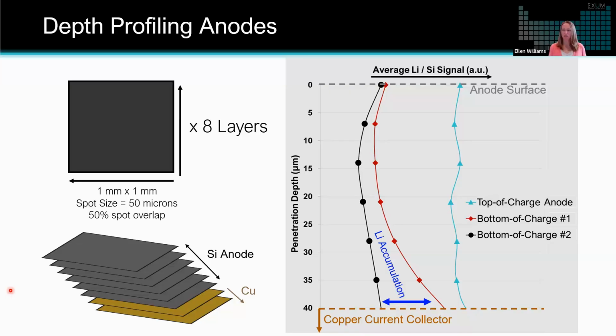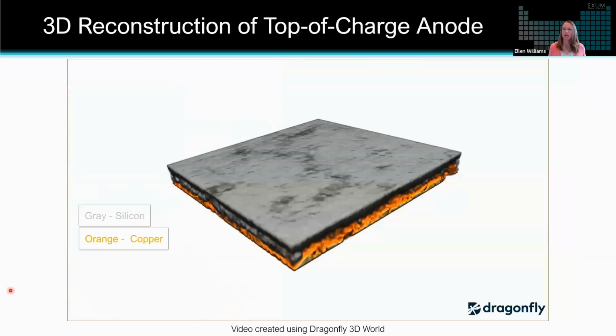So is this lithium accumulation potentially detrimental? Could this potentially turn into some lithium plating? All of this is very helpful to understand as you are developing an appropriate cell geometry and formation cycling process. Now, the final piece of the study that I want to show is what this actually looks like in 3 dimensions. So rather than just averaging and integrating across these different layers, let's take a look at each one of these voxels in 3 dimensions and see those different elements that were identified.